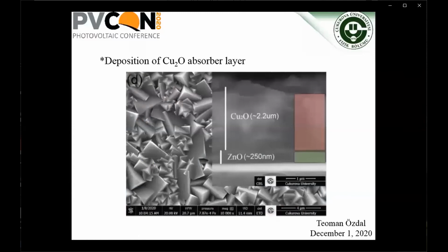SEM image shows cuprous oxide surface and cross-section of our zinc oxide cuprous oxide device. The cubic structure of cuprous oxide can be seen from the surface image. Here we can see the cubic structures. Zinc oxide, cuprous oxide. The thickness of the cuprous oxide was about 2.2 micrometers here.